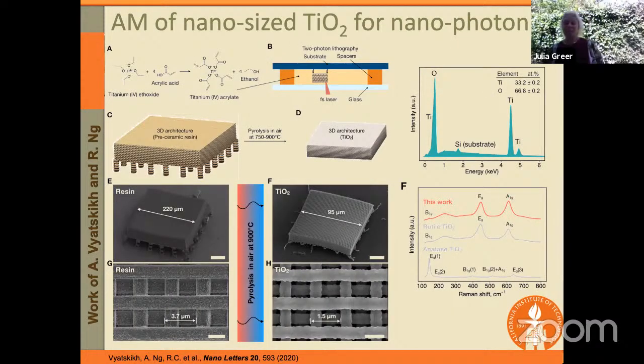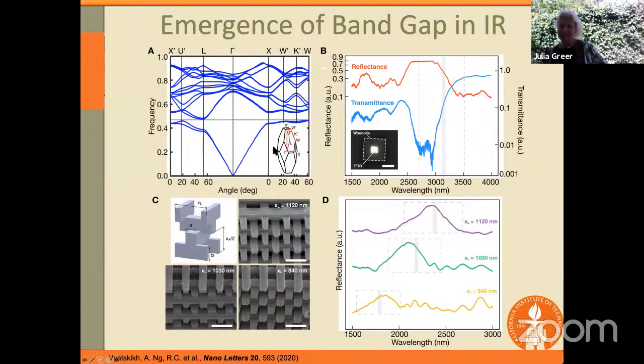Now, taking this one step further and venturing into the world of metal oxides. For example, titanium dioxide is a very useful material for nanophotonics. And what you can see here is it's a similar process, but now we have the titanium ion. Of course, it's 4-valent, and so it's coordinated with 4 different alkyl chains here. And so as we're acrylating it and creating this cross-linked network, what we end up with is a woodpile architecture of rutile titania. And what's amazing is that we can induce a photonic band gap.